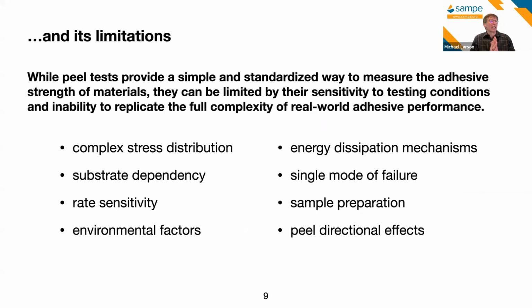include things like complex stress distributions, which, for those of you who have done analyses here, it is pretty complicated what's going on at the leading edge of a failure for bonds. Substrate dependency, so we standardize these in peel tests, but that can look nothing like the actual materials that we're trying to bond together. Rate sensitivity plays a role. It's hard to get a peel test at one rate and sensibly apply that to a different rate that we would have in service. Environmental factors. The mode of failure is typically a single mode for peel tests. We usually have multi-mode failure going on in real situations. Our sample preparation goes a long way to adding to that statistical distribution. Directional effects for our adhesive, and the nature of the substrates.